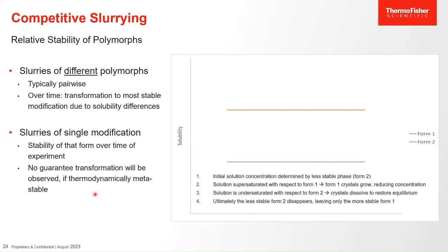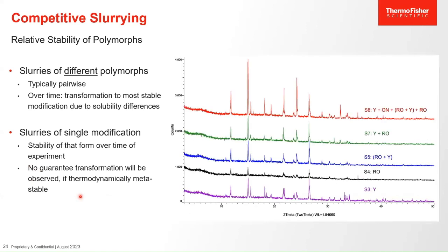A single slurry experiment of a given polymorph only tells you about the stability of that form over the time of the experiment. There is no guarantee that you will see a transformation to a more stable form if it exists. So at the end of a good competitive slurrying experiment, you should have evidence as to which form is the most stable. And this is an example taken from the ROY screening test.